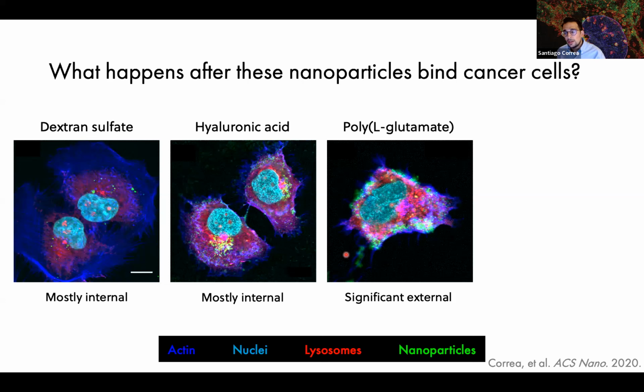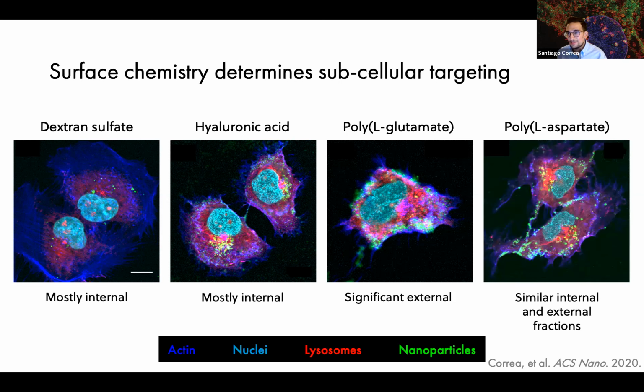a few hours. We were expecting that the polyaspartate system would be quite similar, since those two polymers differ only by a single methylene group. But we were again surprised to see that this polyaspartate actually behaved pretty distinctly from polyglutamate. And if anything, it is almost a hybrid result between the hyaluronic acid and poly-L-glutamate. And by hybrid result, I mean that we're seeing this retention of nanoparticle on the surface.